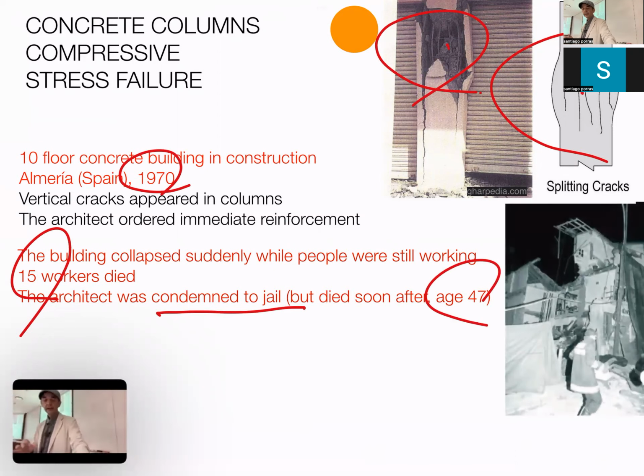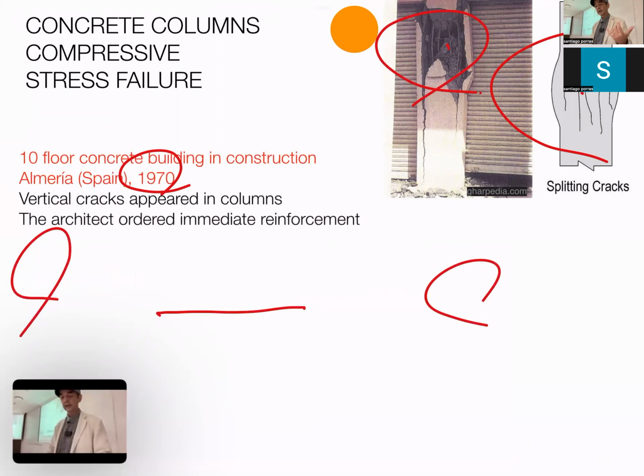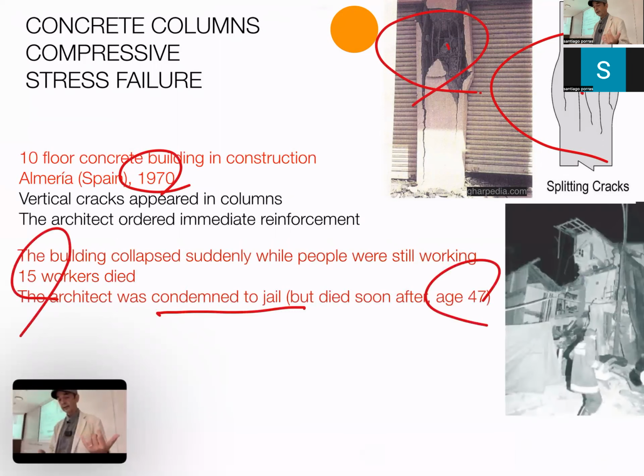In the end, it was discovered that the cement maker had saved money by adding too much lime to the mix. So the hardening was much slower than usual. But the point is, it was a very painful thing, those vertical cracks. Retraction cracks of this kind are okay, but cracks in the column are serious, especially when they are clear, they're persistent, and they appear there, right? So don't forget them. Then about recycling, you can read.